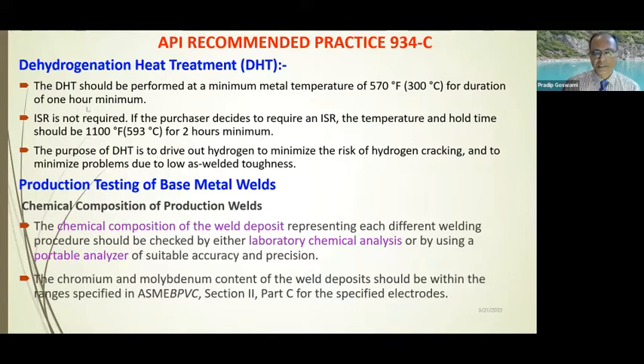The purpose of the DHT, as all of you know, is to drive out the hydrogen from the weld to minimize the risk of hydrogen cracking and to minimize the problem related to weld toughness. In line with that, we have the production testing requirements of the base metal welds. We have the chemical composition of the production welds, which should be determined either by laboratory chemical analysis or by a portable analyzer, typically what we call PMI. The PMI definitely needs to have suitable accuracy and precision. And the chrome and moly content in the welds shall meet Section 2 Part C requirements for the specific type of welding consumable used.